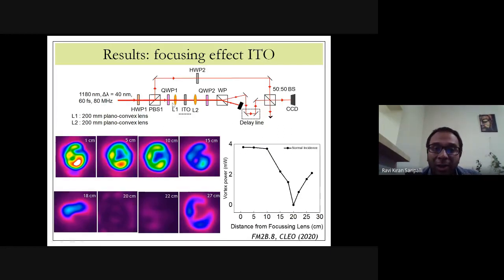So when we are at the focus of the lens, you are in the non-paraxial regime. I mean, more towards a non-paraxial regime. But when you are very close to the lens, you are in the paraxial regime, and that is what they have shown. So this is a 20 centimeter lens. That is what we have shown. When you are at the focus, your spin orbit interaction and vortex generation is very low, and when you are away from the focus, then your spin orbit interaction is much larger. And this is consistent with the simulation.